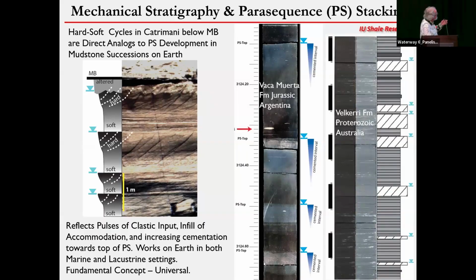Another aspect that we observed just below the marker band, like here's a marker band, okay, here's the altered zone below it. If you look at stratigraphy underneath it, it's a succession of soft to hard, soft to hard, soft to hard packages, which is also marked by the dying out of fractures in the softer intervals. What this reflects to me and my colleagues is that we have pulses of clastic input, infill accommodation, and then we get increasing cementation towards the top of the parasequences.